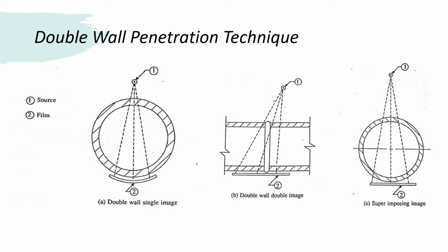The radiation source is generally kept on the pipe or very near to the outer diameter and just near the weld, so that the source side weld is not falling on the film side weld. This technique is employed for pipes with an outer diameter of less than 90 mm. The IQI is placed on the film side.